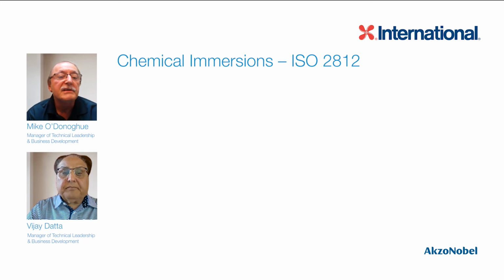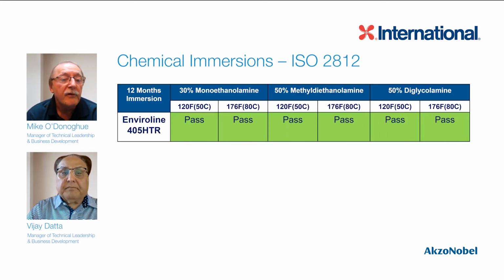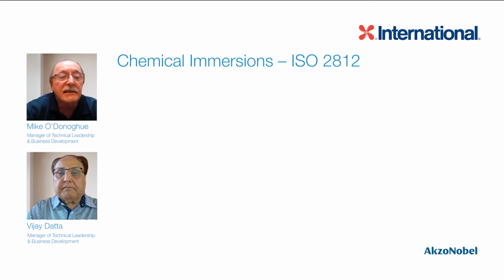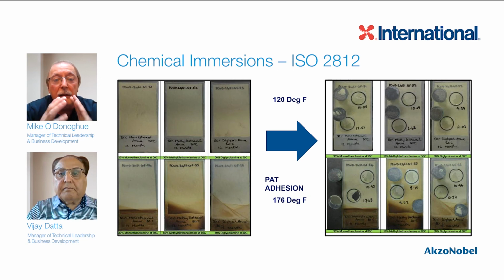With amine chemical immersion testing on coupons, we found that the Enviroline 405 HTR passes 120 Fahrenheit all the way to 176 Fahrenheit, which is 80 centigrade. You'll see in each of the solutions, one being 30% monoethanolamine, 50% methyl diethanolamine, I can hardly say it, 50% diglycolamine, it passes all of these particular tests. So it's particularly resistant because of the very thing we were talking about earlier, where the cross-link density of this coating is particularly very good, very tight cross-link density.